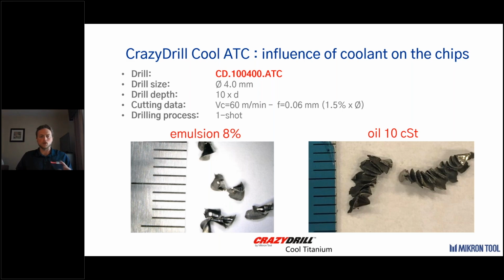So what we're seeing here is the water base is pulling the heat away a little bit more effectively, causing that chip to form at a greater rate. On the right side, where the oil is coming in and not transferring that heat quite as effectively, we see the material staying a little bit more malleable and causing that rippling effect. To treat or diagnose a situation like we see on the right, it's been my experience to increase feed in relationship to the running parameters to give it a little bit more body and then break that chip more effectively.